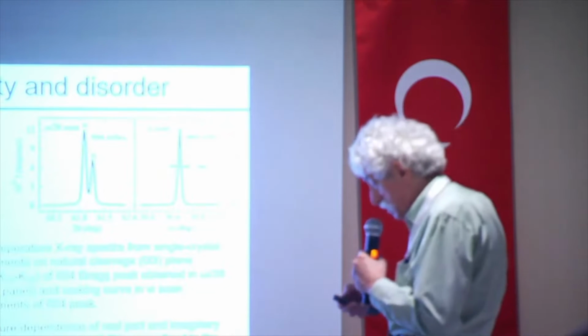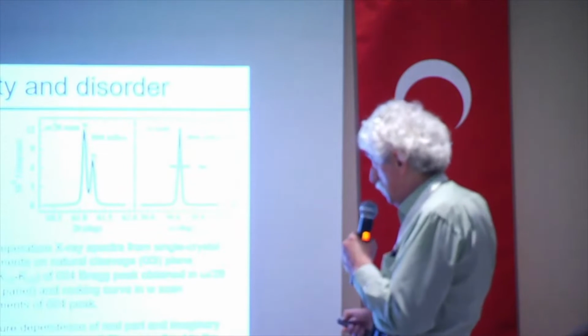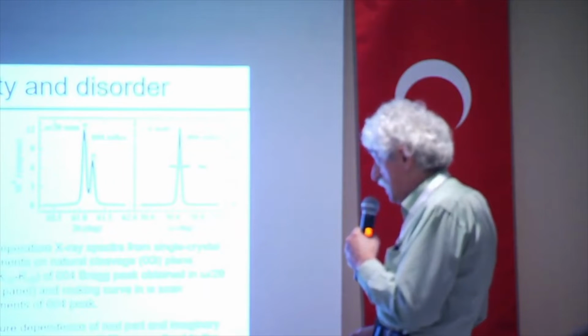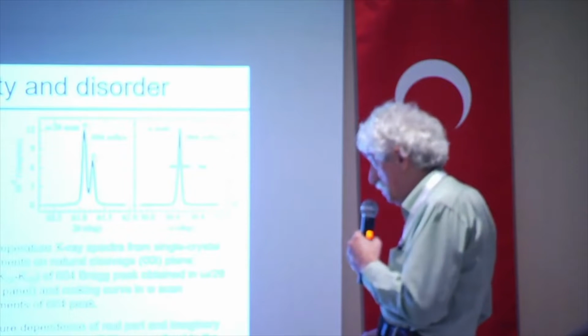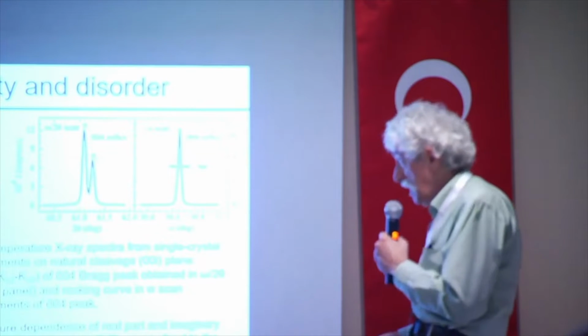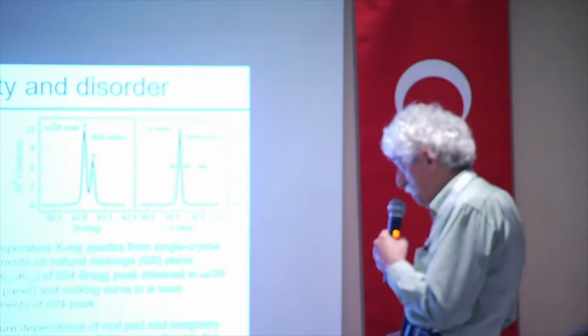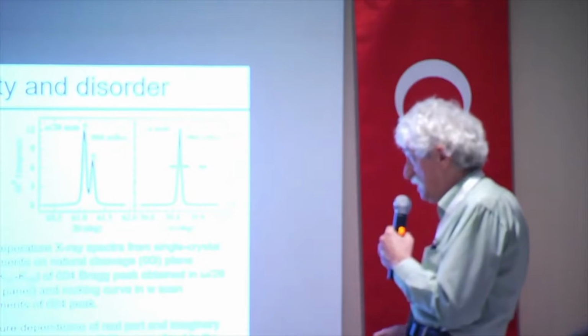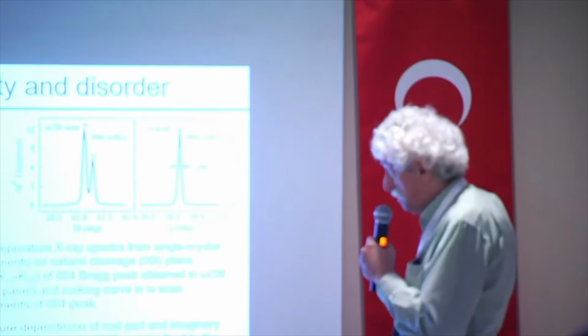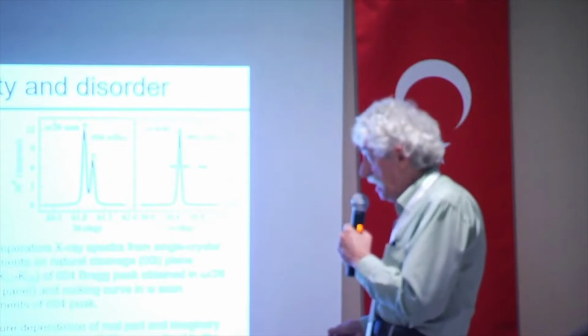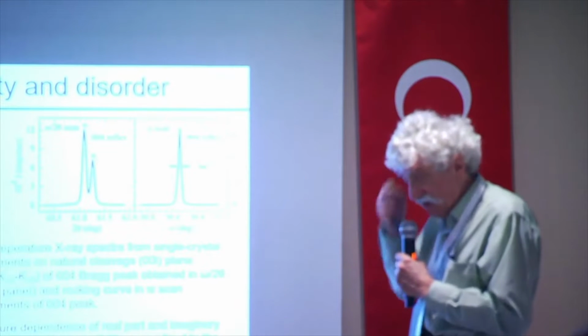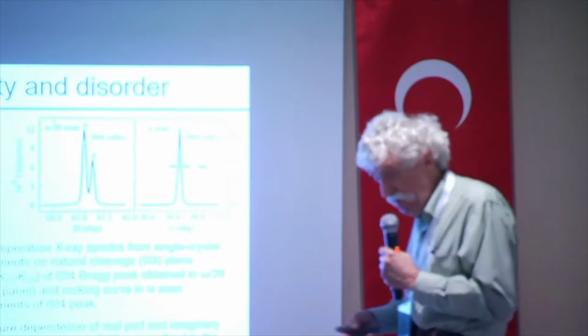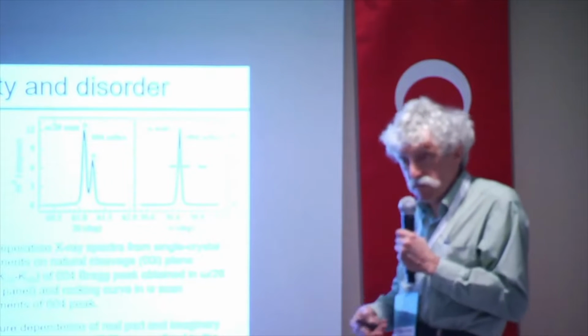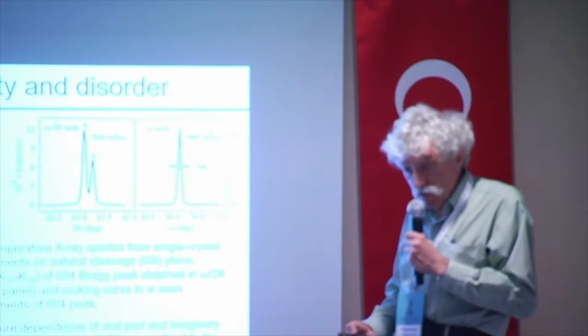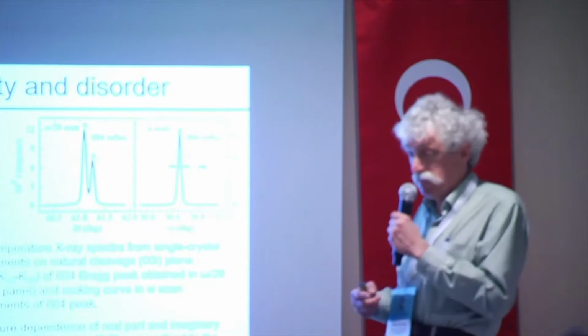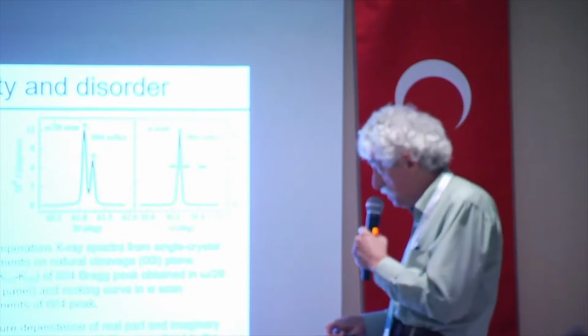So we decided to put all of the crystals which we grew in one picture, and compare with the width of the (004) crystallographic peak. And we found that if the peak is very wide, the transition is extremely sharp. But if the peak is very narrow, the transition is extremely bad. This is completely opposite to what we have intuitively. Because intuitively you think that if you have very high quality crystallographic material, it should be a very good superconducting material. But this result is completely opposite.